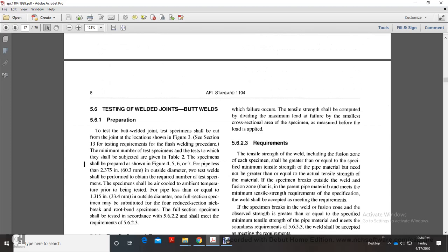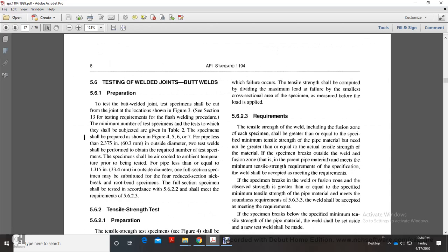5.6 Testing of welded joints, butt welds. Preparation to test the butt weld. The test specimens should be cut from the joint location shown in Figure 3, Section 13. Testing requirements of the welding procedure. Minimum number of test specimens. Tests shall be performed as given in Table 2. Specimens shall be prepared as in Figures 4, 5, 6, and 7.